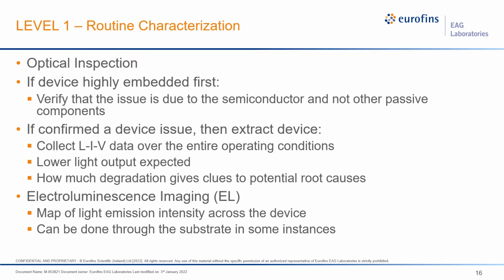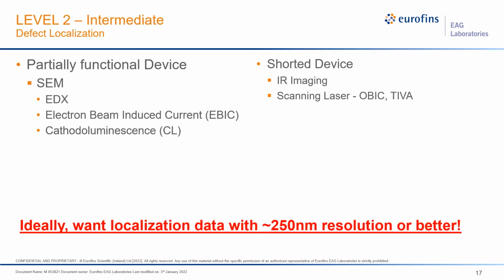But in this case, we have a short, right? So after the stress test, we know we have this ohmic behavior now. So we don't really have a partially functional device. For doing intermediate defect localization, if we did have a partially functional device, we would probably try something like SEM or electroluminescence imaging to try to hone in on where the defect is. But since we know we have a shorted device in this case, we're going to use this scanning laser technique, or OBIRCH, to give us our first indications of where in this millimeter square die the defect is.